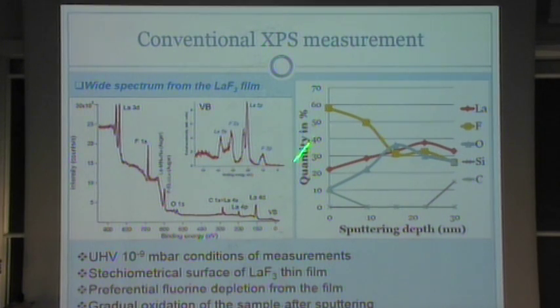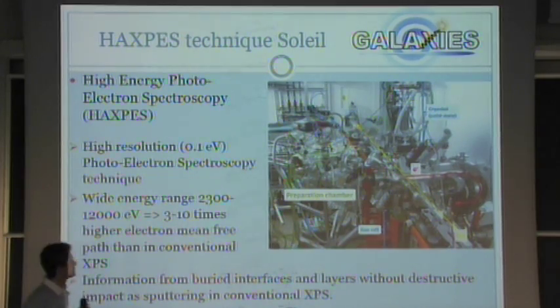So through this technique, we've done a layer-by-layer analysis of our structures, and as you can see, at the beginning you've got lanthanum fluoride, so 20% of lanthanum and 60% of fluorine, but with depth, you can see that oxygen appears. Where does it come from? Lanthanum oxofluoride is already a different material. It has different conductivity properties. It was quite a question, and to answer this question, another state-of-the-art technique, high-energy photoelectron spectroscopy at a synchrotron,